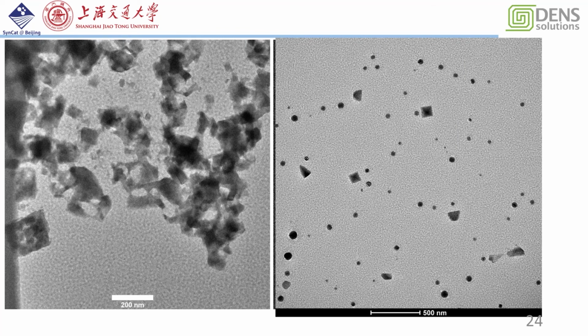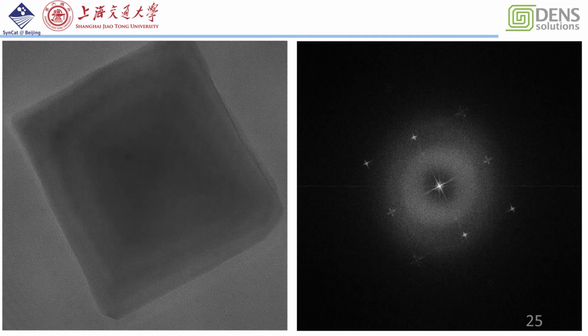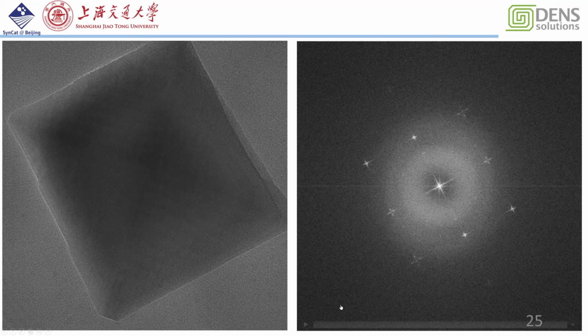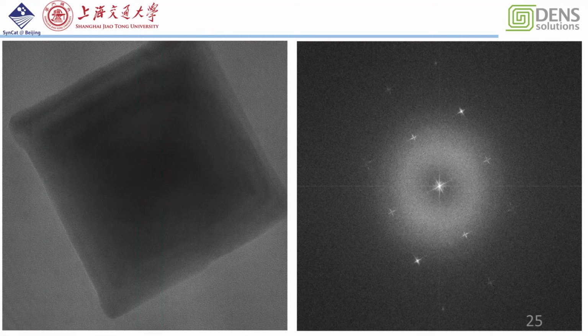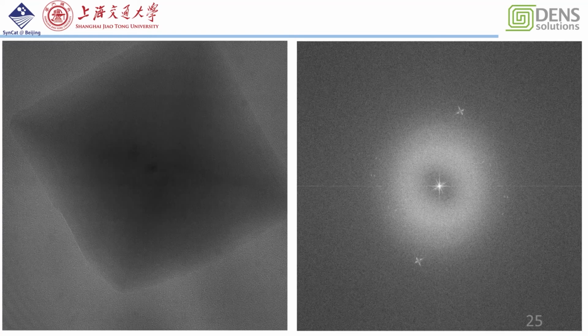But what happened when we increase the temperature higher than 800 degrees, and how does the reduction of the magnetite go? And we found very interesting information. This is a reduction of the octahedral magnetite at about 850 degrees. And we see the moiré pattern changing periodically during the reduction process. And this is the FFT of this nanoparticle. And we can see the very interesting periodical change in the FFT pattern during the reduction process.